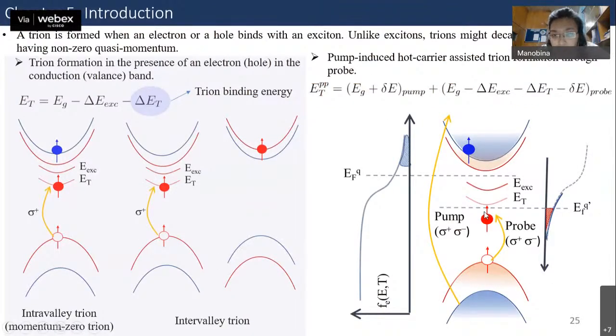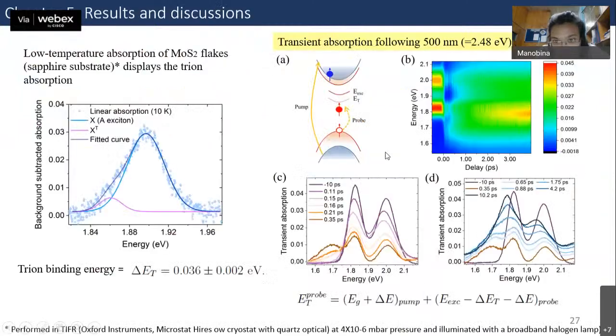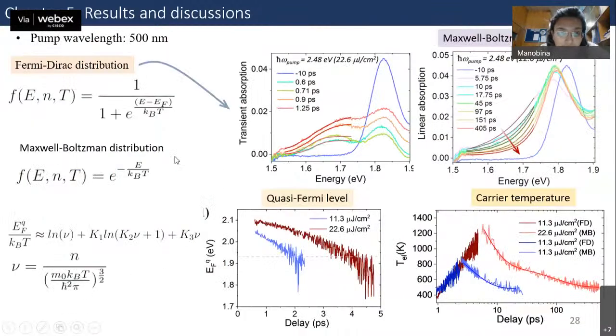Here we study this trion formation dynamics through pump probe technique, where in steady state for a trion we have some doping and we excite an electron hole pair. But in pump probe, through pump we excite some carriers, and through probe we excite another pair, and it forms a trion. So here we observe the time dependent evolution of a trion feature, and from that we measure this carrier temperature over time, and this we could track the quasi-Fermi levels and its evolution over time.